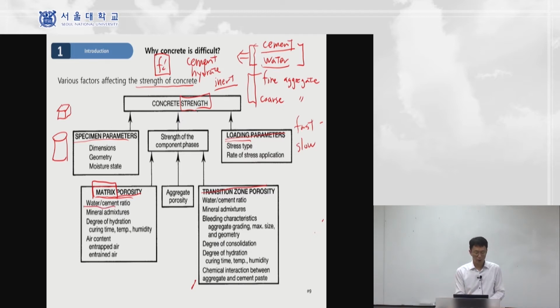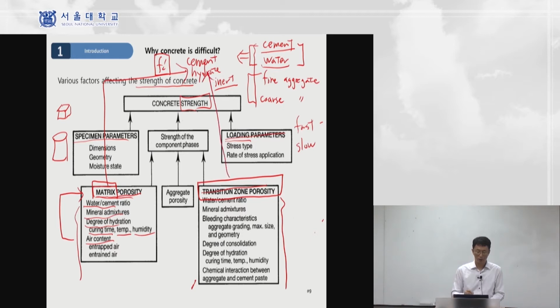Water to cement ratio, mineral admixture, degree of hydration, curing time and temperature, humidity, air content, all these parameters will affect the matrix porosity, and this will affect the properties of the cement hydrate. Okay? An even more difficult factor is the transition zone porosity here. Okay? There are even more variables that affect the transition zone porosity of the cement hydrate.